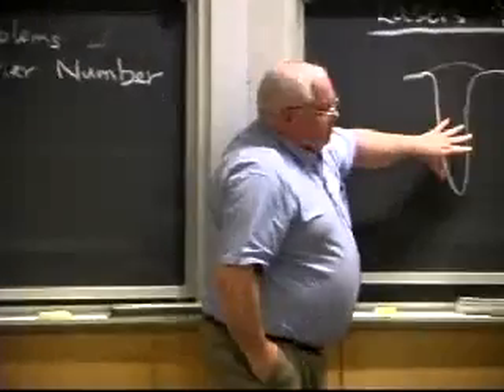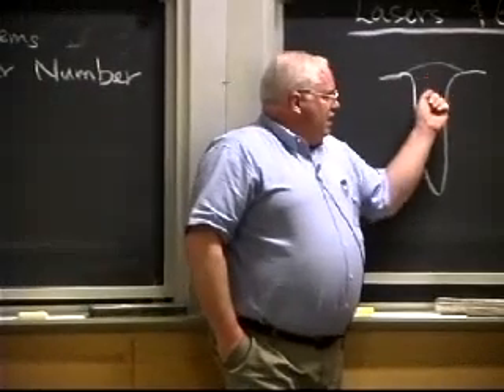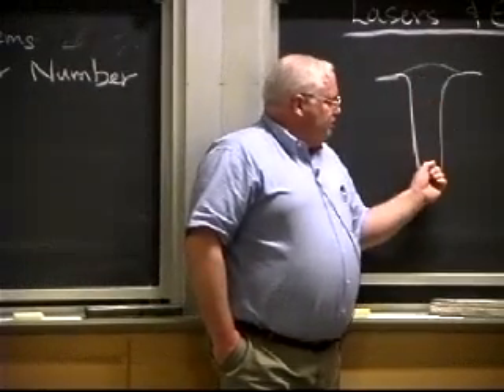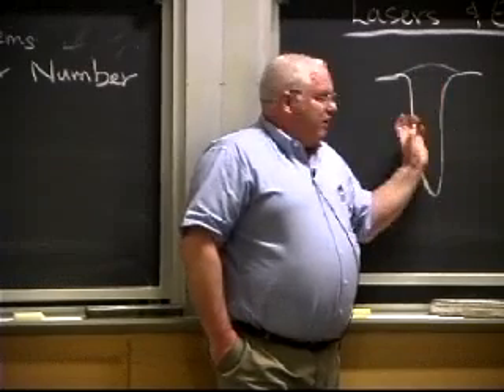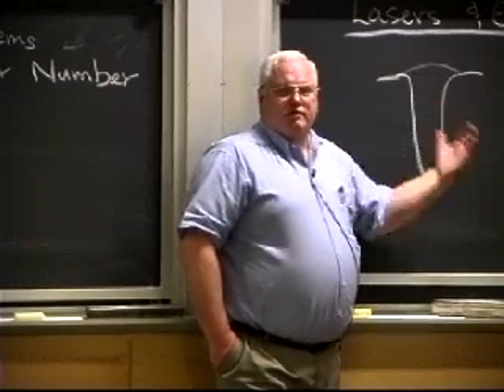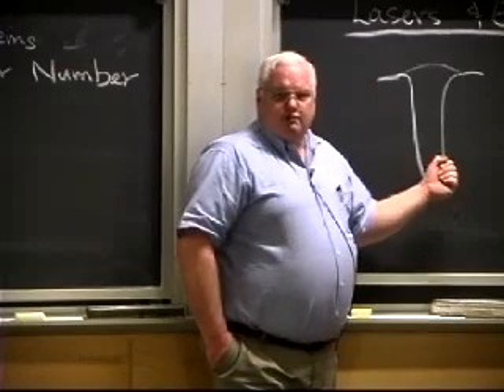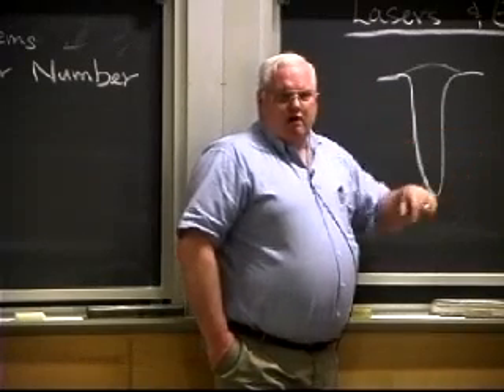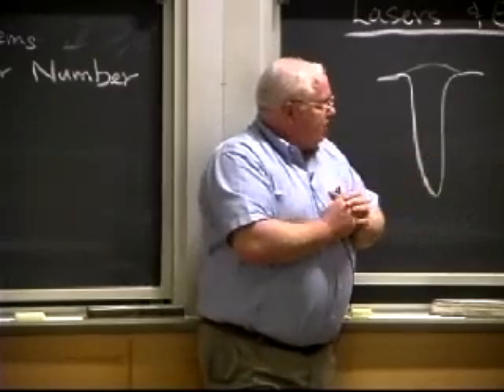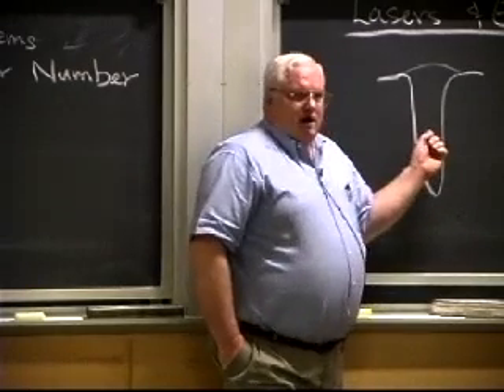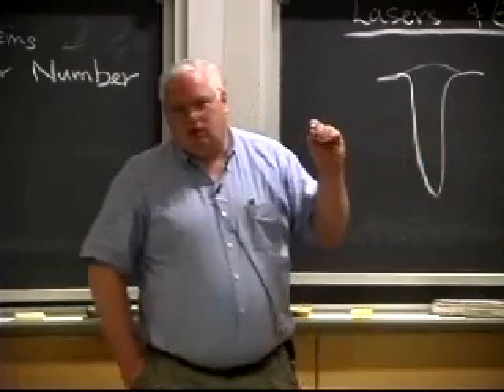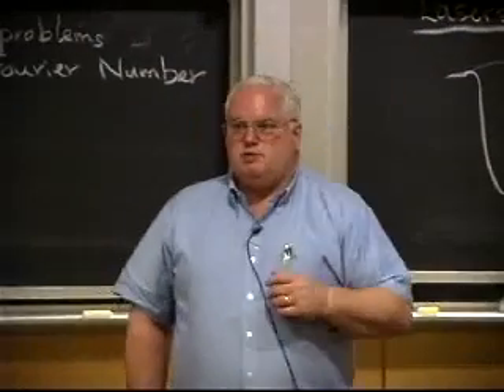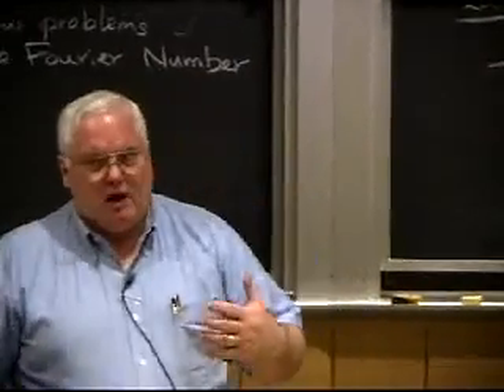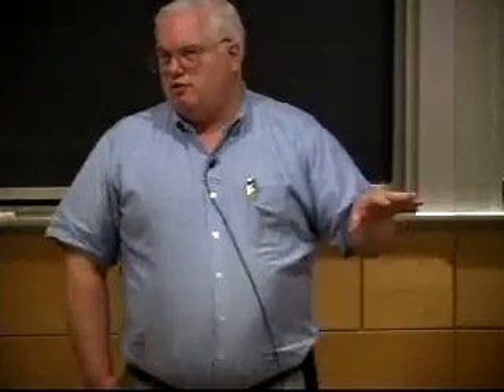So typically you only want a depth to width ratio of about 10, and in fact, when you use these types of power densities, you're going to essentially drill a hole, and then the metal will flow around behind it. And you saw the movie from the Japanese Welding Research Institute from 1980 that shows laser welding on Pyrex glass and electron beam welding and how the metal flows around behind to fill in and solidify. Now, it turns out you cannot drill these holes in less than a millisecond, and it's because of the inertia of the metal. You can liquefy the metal, but typically it takes about 1 to 10 milliseconds for the metal to be pushed aside by the forces that are generated in this process.